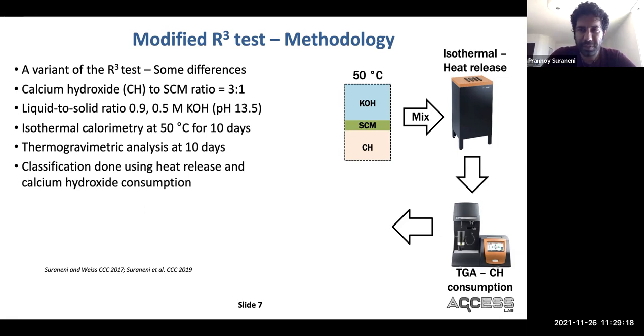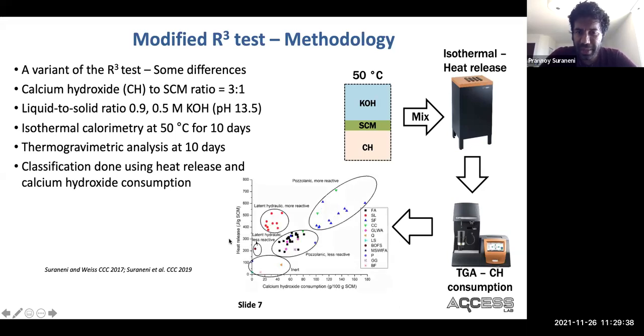So this test is interesting because most reactivity tests measure just one parameter, like heat release. Here we are measuring two things. The isothermal calorimetry is giving you the heat release, and the thermogravimetric analysis is giving you the calcium hydroxide consumption. Based on these two parameters, we are classifying the supplementary cementitious materials. So here is a plot of heat release versus calcium hydroxide consumption. And I'll talk a little bit more about the classification in the next couple of slides.